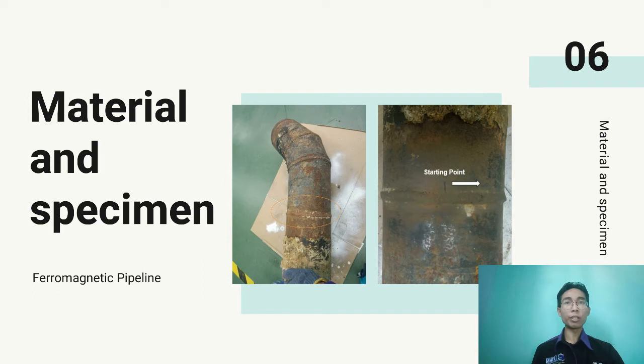Okay, the material used for this study is a ferromagnetic material pipe, which was discarded from a certain factory because of leakage from it. Leakage happened because of the crack formed in the weldment of this pipeline. The specimen is made of ferromagnetic material, which is suitable for our ECT inspection. In this thesis, the inspection will only investigate one weldment, which is the circle in the photo, and the inspection of the welding on this pipeline will begin at the starting point and encircle the specimen pipe by following the arrow until it reaches the starting point again.